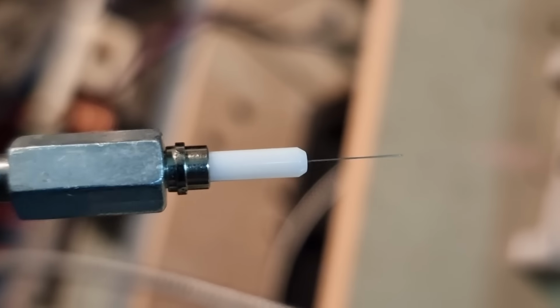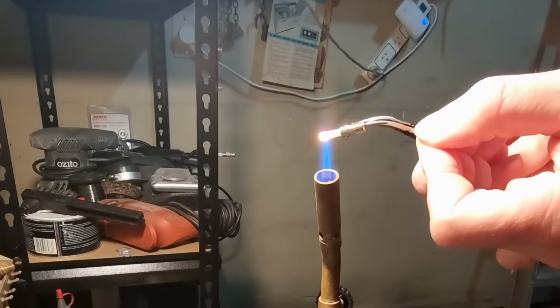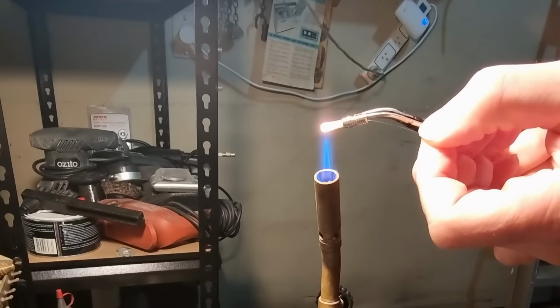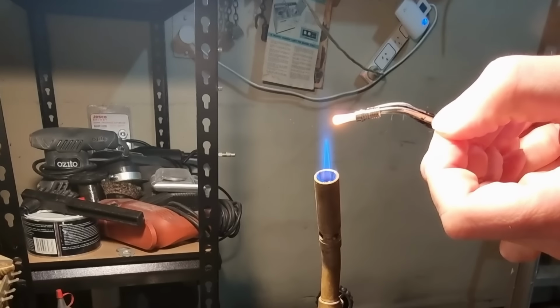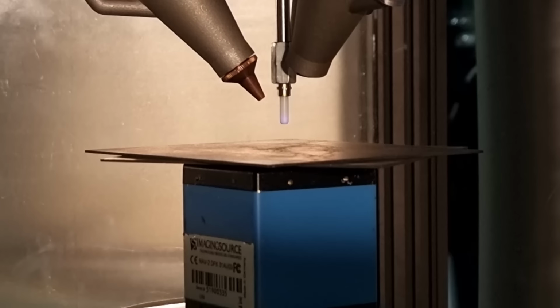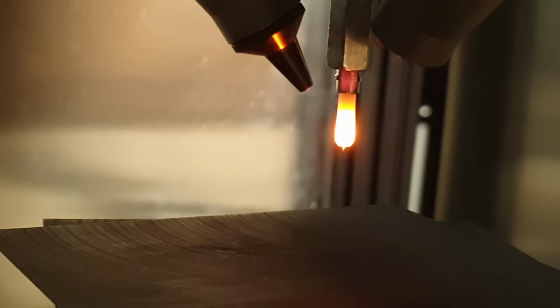I had to know if this would absorb or reflect laser light and to find out whether it could even handle the heat. The first thing I did was to expose it to the flame of a propane torch, and it did swell quite a lot, but never cracked. I also focused a laser on it, exposing it to the maximum power. It seemed fairly transparent to the beam, so I fed some wire through it and tested it again. And that did not go well.